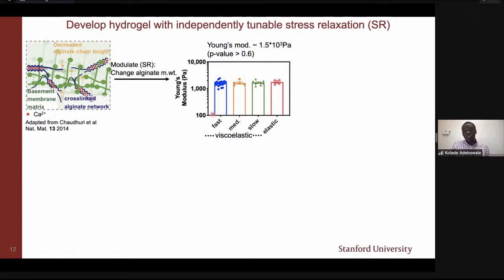That then allows us to make a range of viscoelastic materials that all have the same initial Young's modulus of about 1.5 kilopascal, or a purely elastic polyacrylamide hydrogel that has an initial Young's modulus of about 1.5 kilopascal. So these materials are very compliant. To give you a sense of how compliant they are, a gummy bear has a Young's modulus of about 70 kilopascal. So these hydrogels with an initial Young's modulus of 1.5 kilopascal are quite compliant.